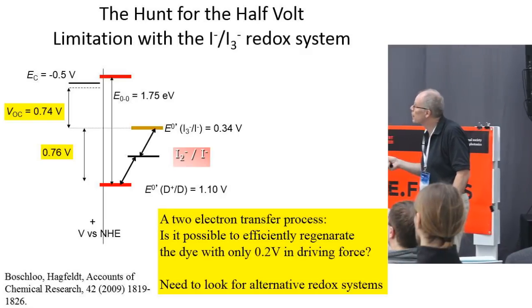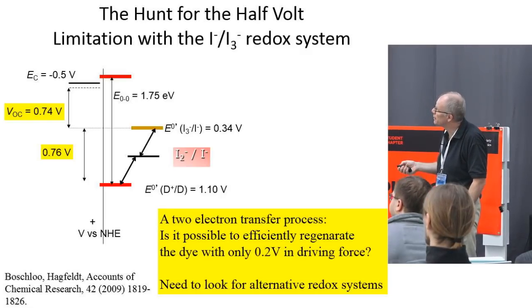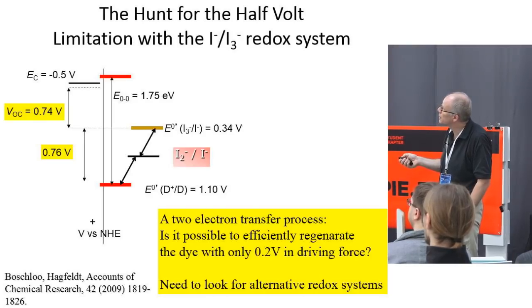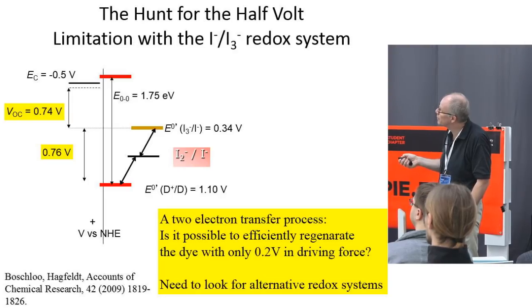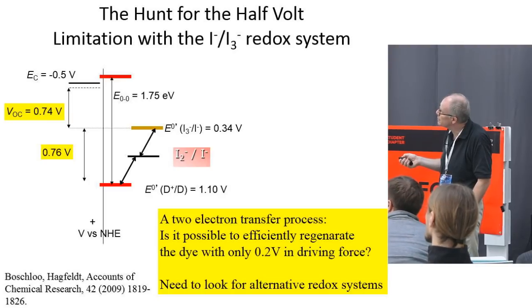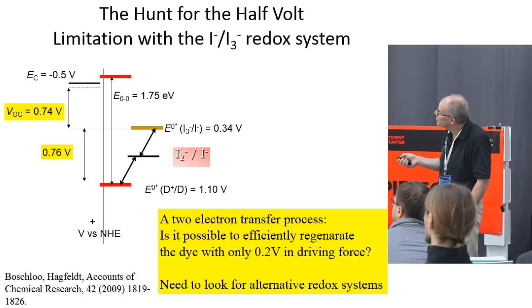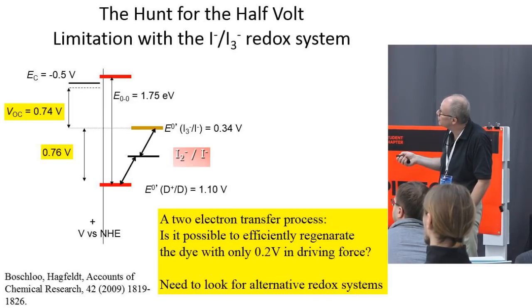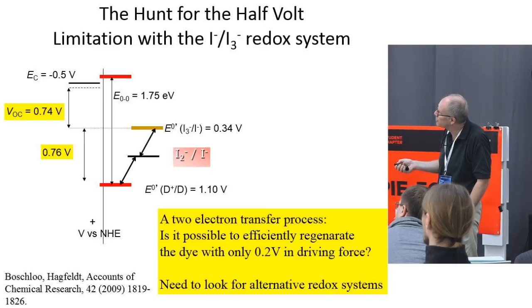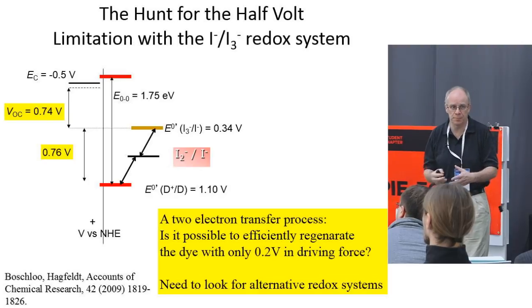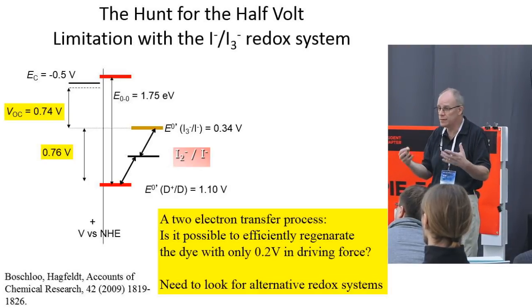Well, we look into the energy levels. This is the HOMO, the ground state of the dye, excited state, conduction band. This is the redox potential of the electrolyte. And the voltage is given by the Fermi level difference to the redox potential. And here, when we map this and measure the numbers, we get quite a big loss, a gap in potential between the redox potential of iodide and the oxidized dye. It's a gap of typically 0.7 volt. And that's a 0.7 volt loss in the system.